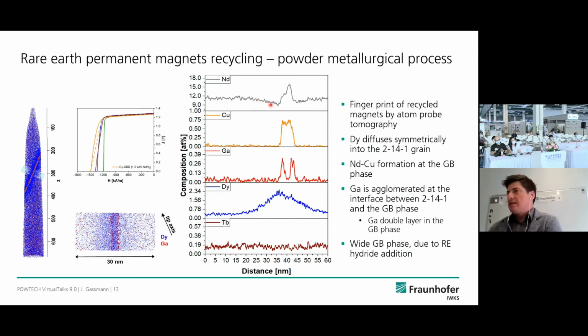So first, one can see, of course, we have an enrichment of neodymium on the grain boundary phase. Also copper and gallium are enriched in the grain boundary, and dysprosium, due to the grain boundary diffusion process, is somehow also diffusing a bit into the core, into the 2-14-1 core. However, what is interesting is this gallium information that it seems to be agglomerated directly at the interface between the 2-14-1 grains and the intergranular phase.